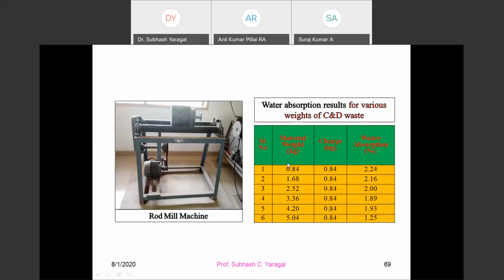For all these, we have studied the water absorption, and it is very interesting to see. If you take the C and D waste around 5 kg, with the charge, the steel rods, at 840 grams, you have the least water absorption. That means this coarse aggregate is processed best compared to the remaining. So I have optimized for each run how much kg of C and D waste can be taken.